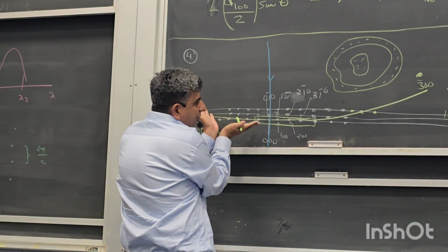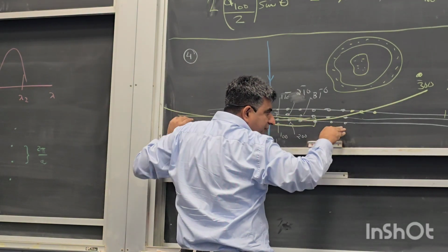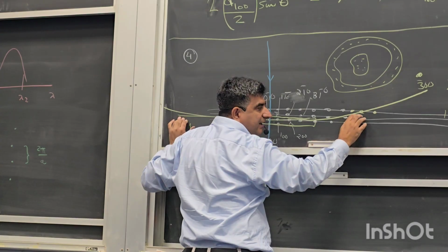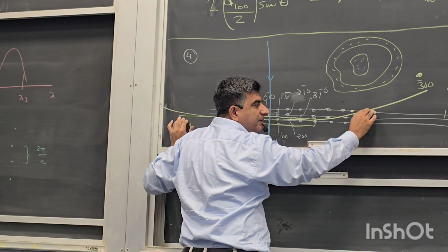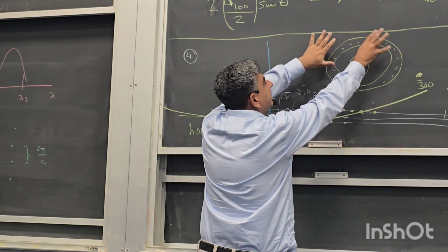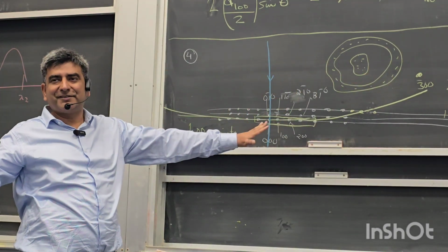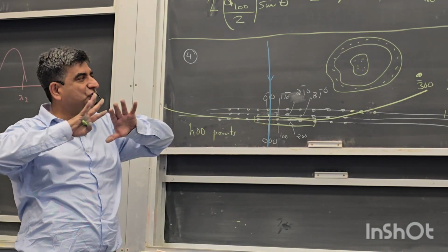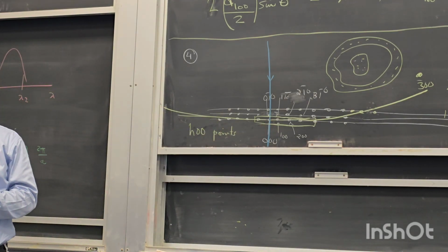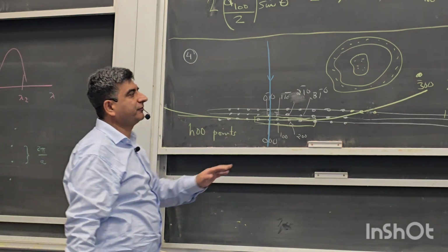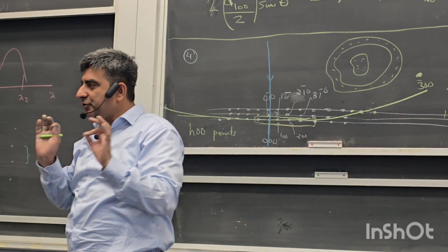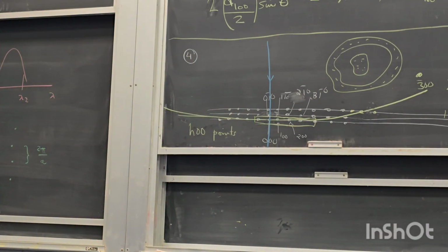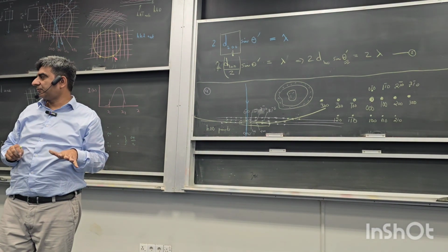Okay, because now this Ewald sphere is going out. When it has diverged from this row, it is not intersecting with any other reciprocal lattice points in the second row. It might intersect with some lattice points in the third or the fourth row. So you'll get another ring when the circle reaches there. Okay, so you'll get zones inside your diffraction pattern. A zero order zone followed by a ring, and this congregation of points is a direct visual signature of the reciprocal lattice. So you can see the reciprocal lattice in a transmission electron microscope.